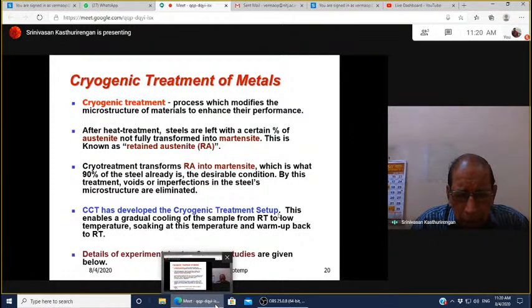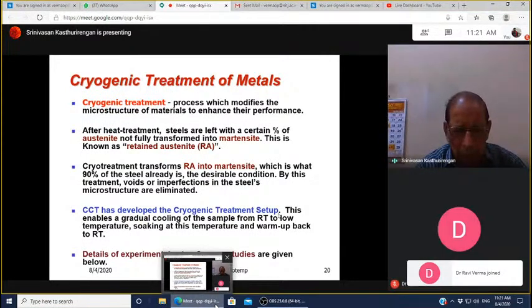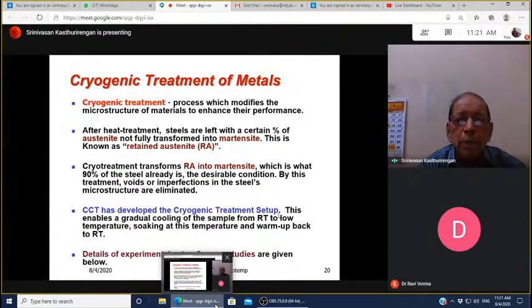After heat treatment, the steels are left with a certain percentage of austenite, which is not fully transformed to martensite. This is known as retained austenite, or RA. The cryogenic treatment transforms the retained austenite into martensite, which is what 90% of the steel already is, the desirable condition. By the cryogenic treatment, the voids and imperfections in the steel structure get eliminated.